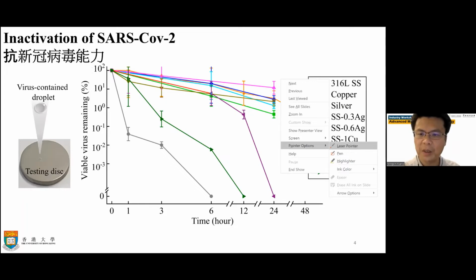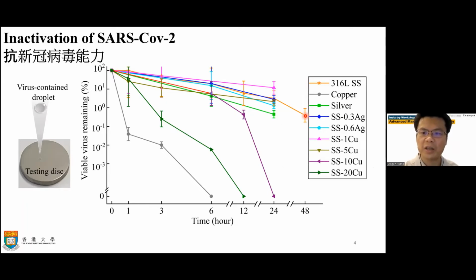This is a very conventional stainless steel. For the conventional stainless steel, you can see that after 24 hours or 48 hours, you still have live virus on the surface, not to mention after a few hours.